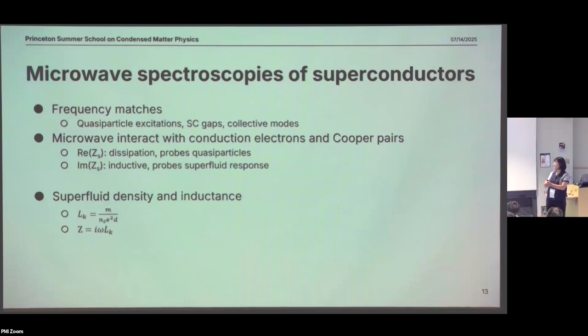So directly, if you get a microwave spectroscopy, then you can already tell a lot of those things. And another thing is that the microwave can interact with both the conduction electrons, in the way that a DC field does, and also Cooper pairs. Because it's oscillating and it probes the kinetic inductance, the real part of the impedance has to do with dissipation, and it probes those quasi-particles. So the imaginary part probes the inductive and the superfluid responses.